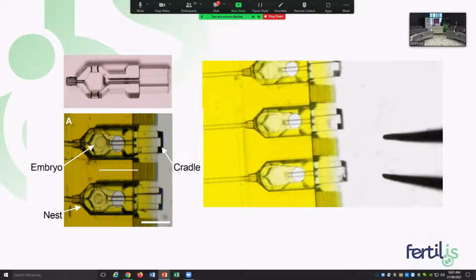I'll quickly run through printing specifications. So the cradles were printed in vat mode using a 20 times objective, a water immersion medium, and transparent low fluorescent resin IP-Opto. Was using a laser power setting of approximately 150 milliwatts, and coarse printing mode was enabled. We were able to print an array of 196 parts in 7 hours and 53 minutes, so 2.5 minutes per part.